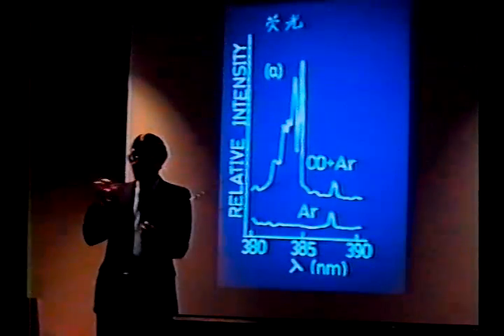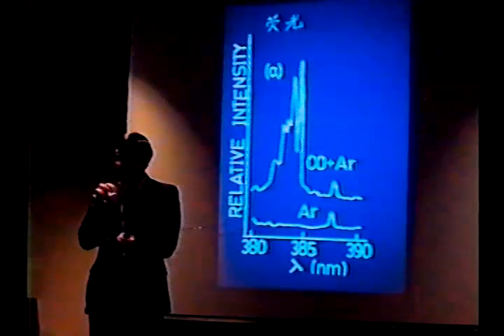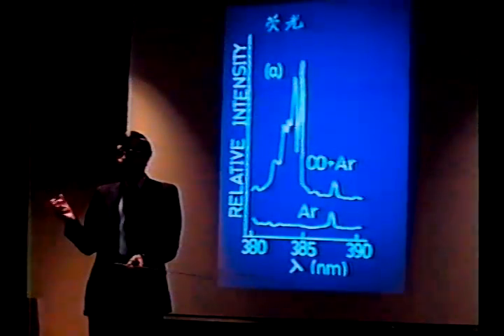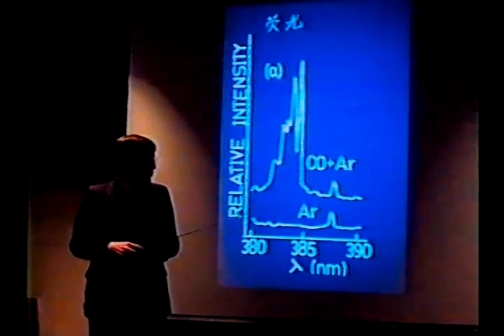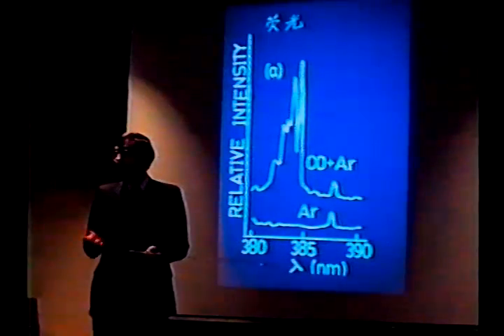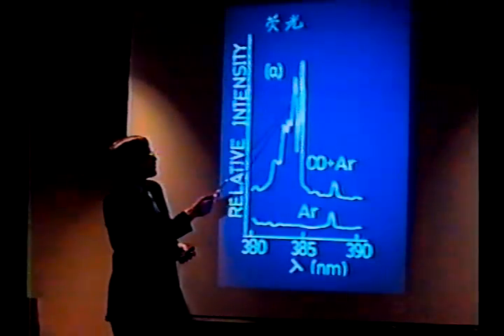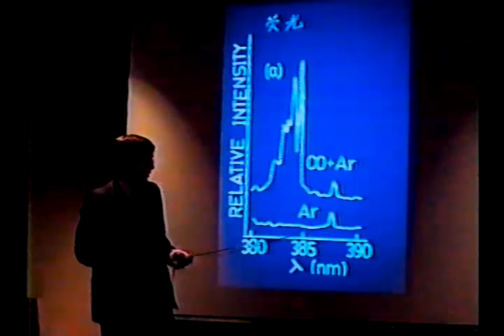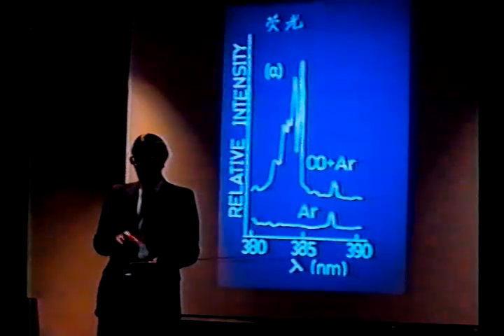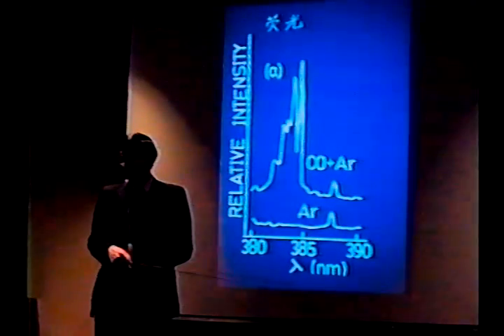Well, what we can do if we put this metal carbonyl into the zeolite is start the plasma, it starts to glow, and we just use a monochromator and a detector to scan this fluorescent spectrum as a function of time. And if we put a wavelength in here for carbon monoxide around 384, we can titrate the amount of carbon monoxide coming off the catalyst. And what's happening here is that all of the carbon monoxide is coming off. None of the metal's coming off, because the atomic metal fluorescence is well known. We don't see any of that. So the metal's staying down there on the zeolite, the carbon monoxide is coming off, stoichiometrically.